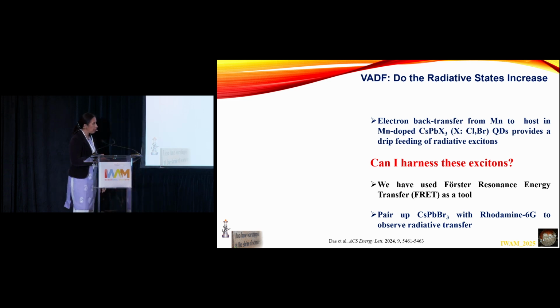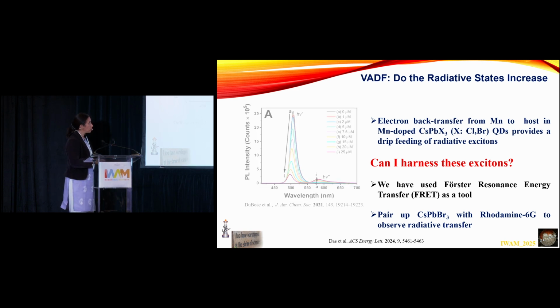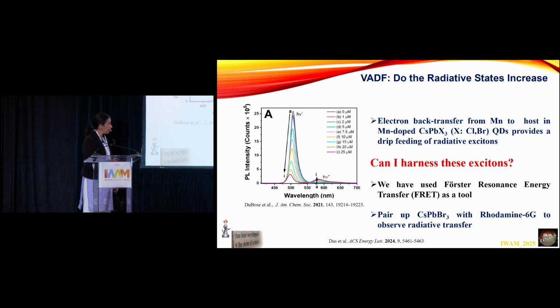So if I pair up the cesium lead bromide with rhodamine 6G, if there is an electron to recombine at the band gap, then there will be an energy transfer. If not, there is going to be no energy transfer. This is not the first time that has been done. This has been done extensively in literature and is pretty well studied. So what people do is, if you just titrate the dye, you see that there is a decrease in the excitonic peak and an increase in the dye peak.